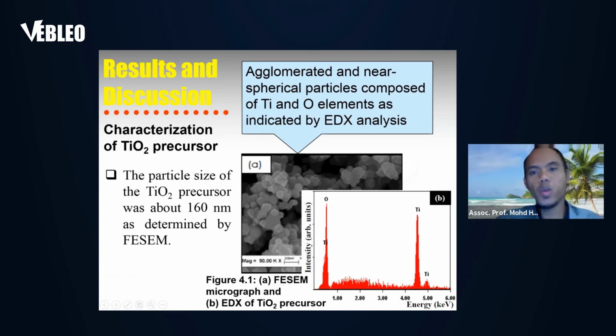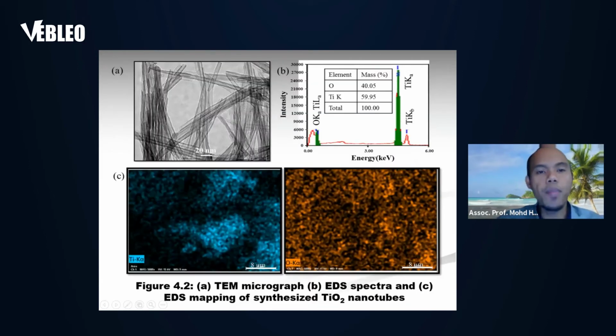After that, we characterize the formation of titanium dioxide nanotubes. Okay, we can see very nice hollow elongated nanostructures. That means titanium dioxide nanotubes were successfully produced using this method. Okay, we use TiO2 powder as a commercial precursor, and then we come out with these very nice titanium dioxide nanotubes.